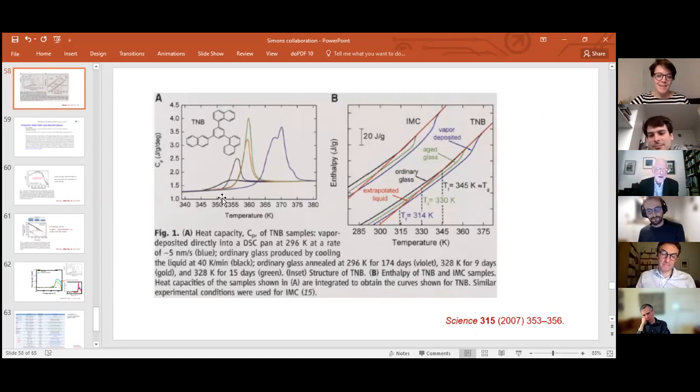So what they're effectively saying is that you heat the glass, it wants to become a liquid. You will detect that happening when the specific heat takes off. And that is very much delayed in these super stable systems. Mm. So it fits in with that idea. I'm not sure Mark Ediger would agree with what I'm about to say, but it is in some way consistent with the idea that these glasses genuinely have difficulty going through the transition into the liquid state. Yes. And that it then propagates in from the surface or something like that. Yeah, at least I don't know about Mark, but I do.